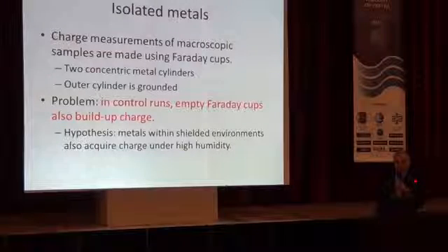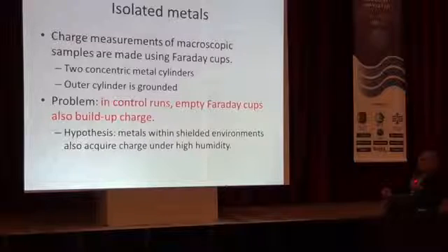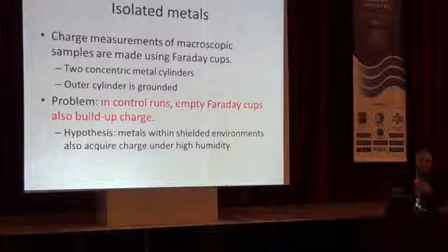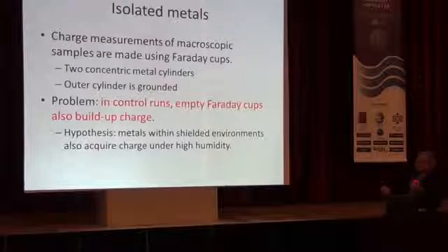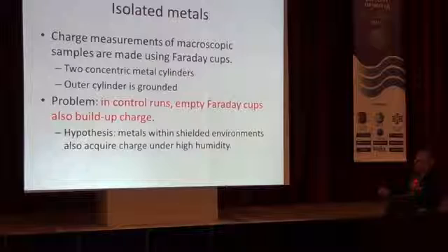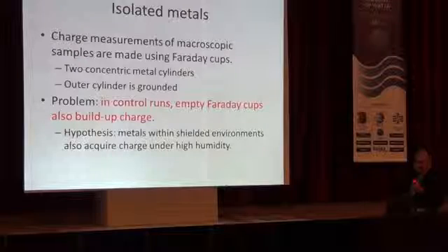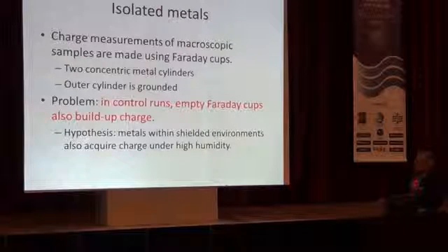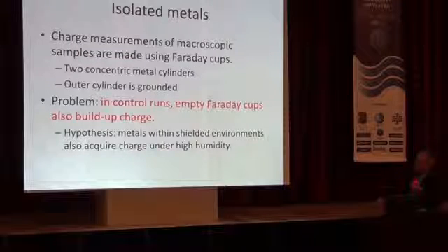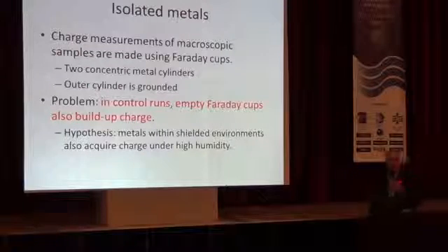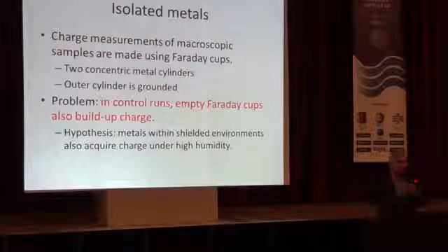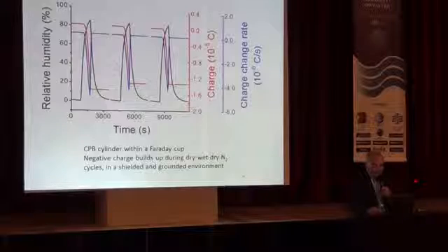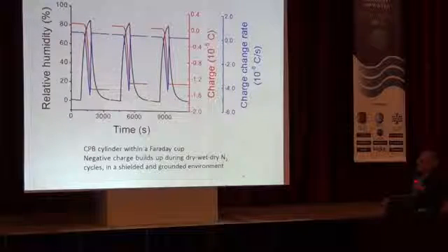So finally, I will mention some metals. When you have isolated metals, to verify the Kelvin measurements that I just showed, we wanted to do direct charge measurements using Faraday cups. When we started doing the Faraday cup measurements, we observed some strange results. So we went into doing control runs with the empty Faraday cups, and we observed that changing the humidity, there was also charge buildup. That you can observe here.